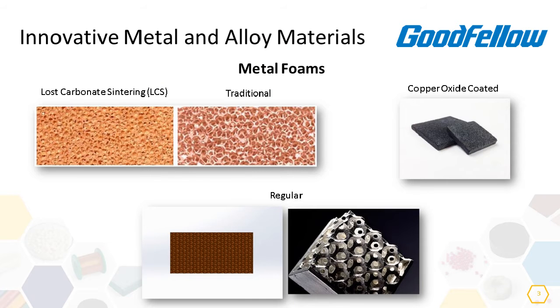On this slide, we are demonstrating different types of metal foams, such as lost carbonate sintering foams, the traditional ones, copper oxide coated foams, and the regular foams. These foams can be aluminium, copper metals, or other metals, even stainless steel. The lost carbonate sintering foams have smaller pores, higher relative density, and high surface area. While the traditional ones have lower relative density, their cell structure is permeable with continuous ligaments, and they're characterized by high surface area to volume ratio and high strength to weight ratio.